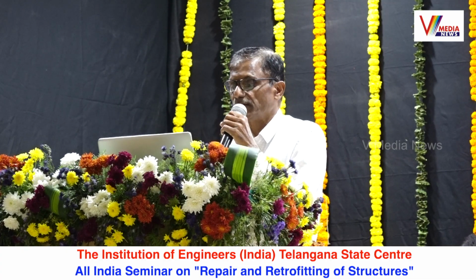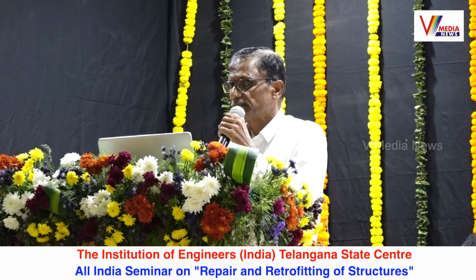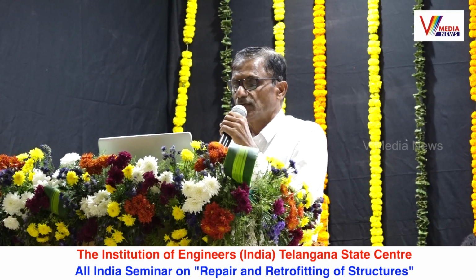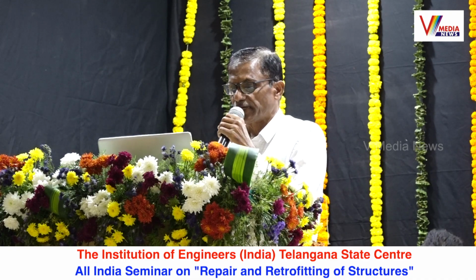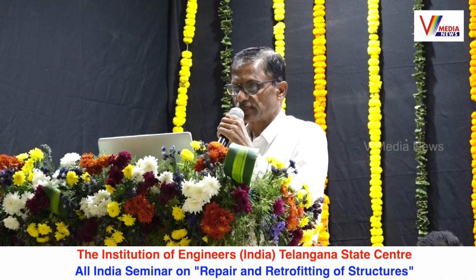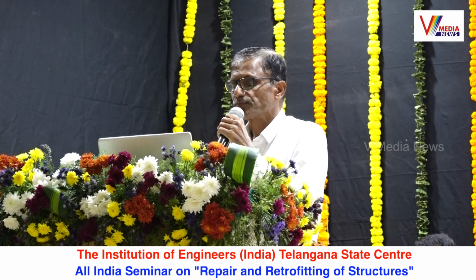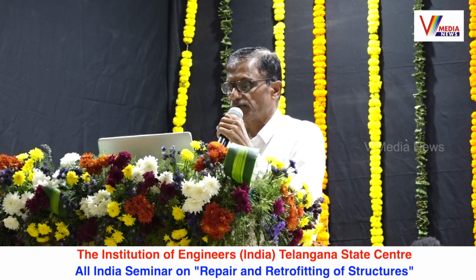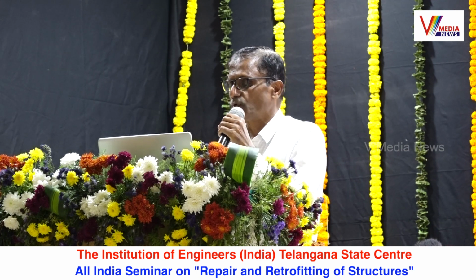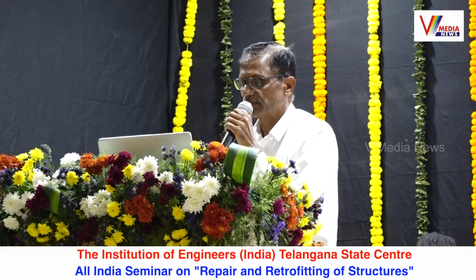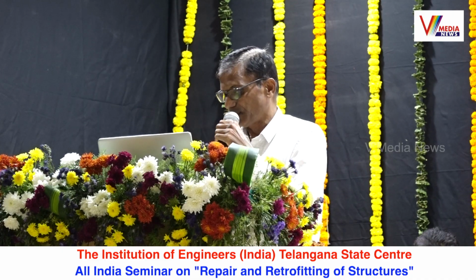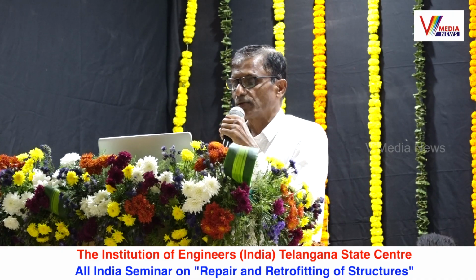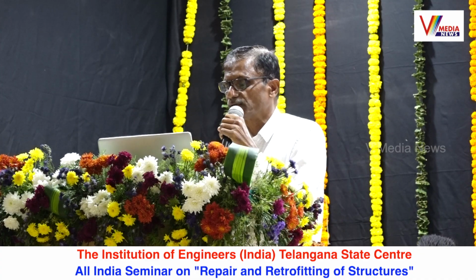As a summary, the fibers generally enhance the durability of geopolymer mortar: they improve water absorption resistance, vary chloride permeability, enhance surface resistance, and reduce shrinkage. As a conclusion, 5% steel fiber content appears to offer the most balanced and beneficial improvement across the multiple durability parameters for geopolymer mortars. These are some of the references.